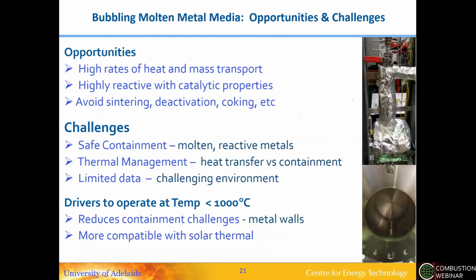But there's also growing interest in bubbling molten metal media as a catalytic reactor. Some of the opportunities of using a bubbling molten metal as the reaction media are that the bubbling generates high rates of heat and mass transport in the reaction path, and the molten metals are both highly reactive and have catalytic properties. And unlike solid catalysts, if carbon is generated on a solid catalyst, it will tend to coke the catalyst. But if it's generated in a molten bath, then this tends to float to the top.